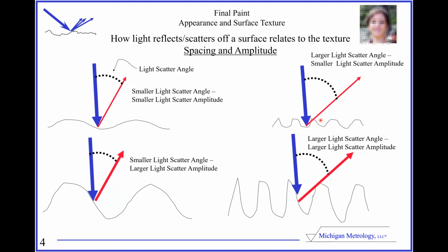This is a very simplified way, but yet you can see how surface texture wavelengths first have to be asked when you're concerned about saying one surface doesn't look the same as another. The question is, why does it not look the same? Is it waviness, meaning is it orange peel, a longer wave distortion problem, or is it more of a short wave hazy thing? That's what you have to be concerned about.